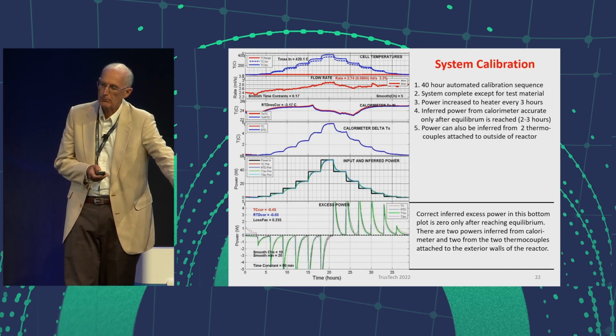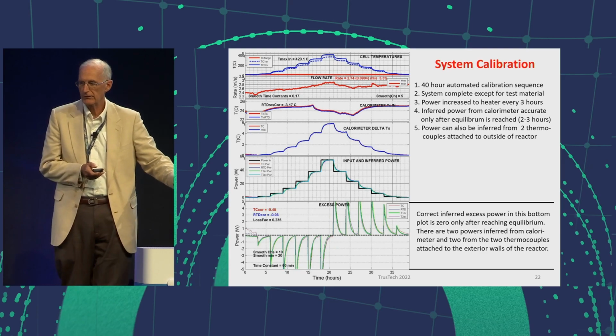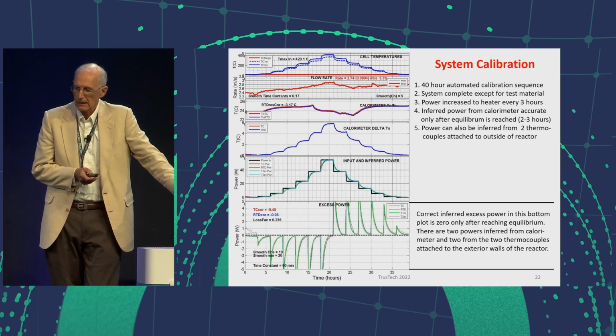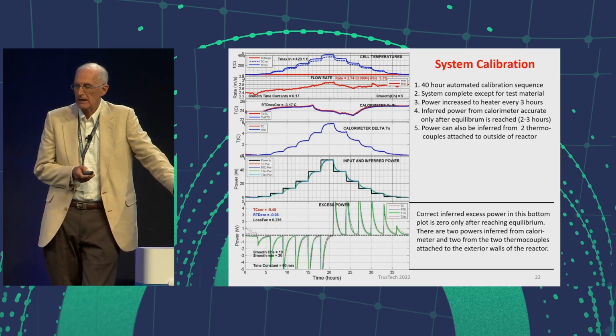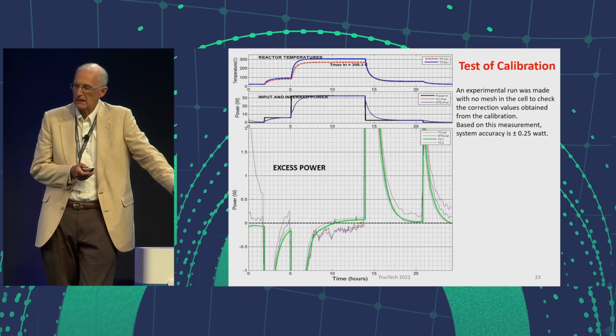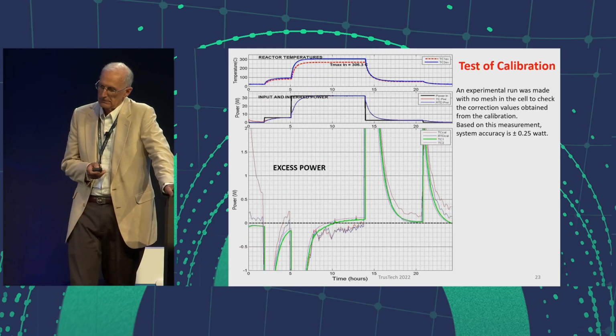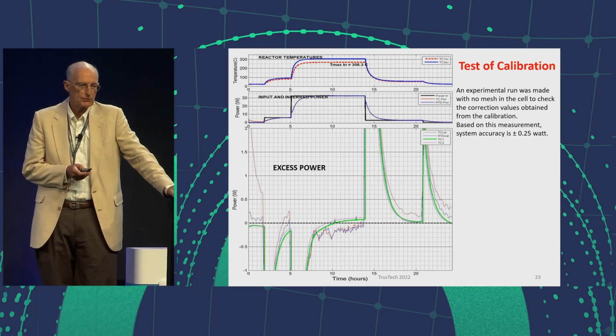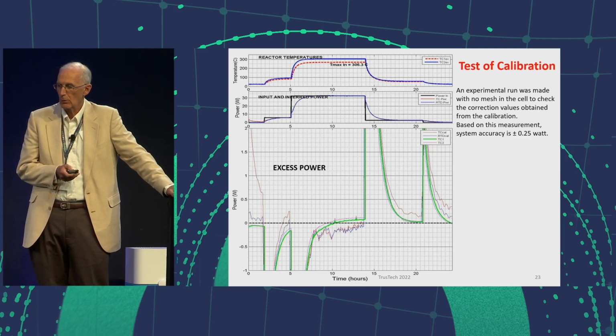This shows the calibration of the system used. This is similar to the data I showed you before. And after I did the calibration, I did a check of it, and it indicated that I had a sensitivity of about plus or minus 0.25 watts, a quarter of a watt.